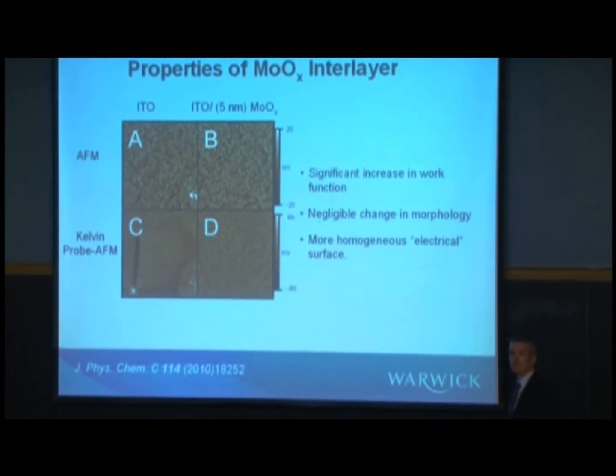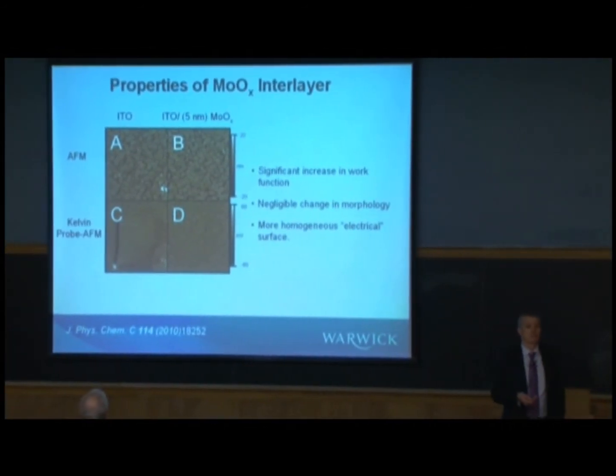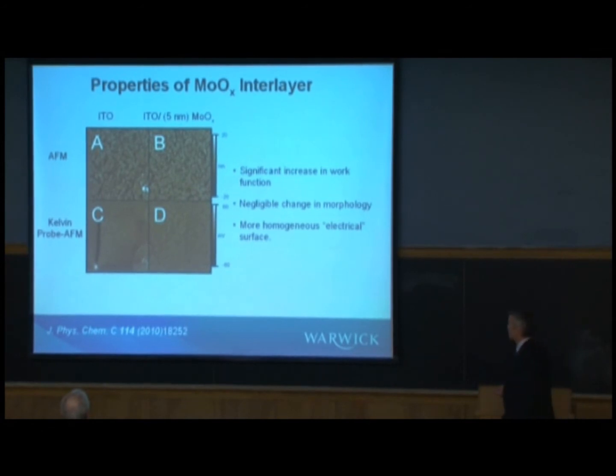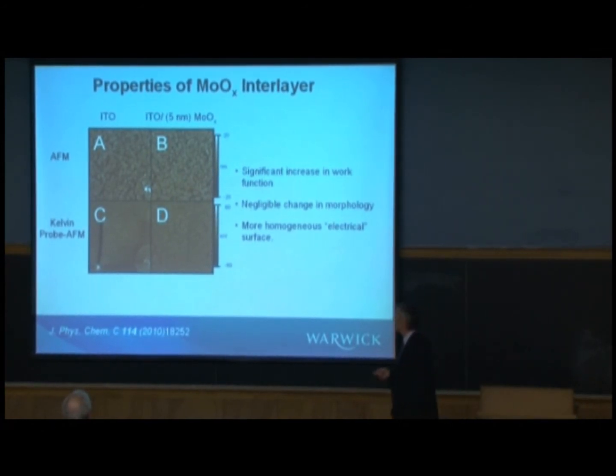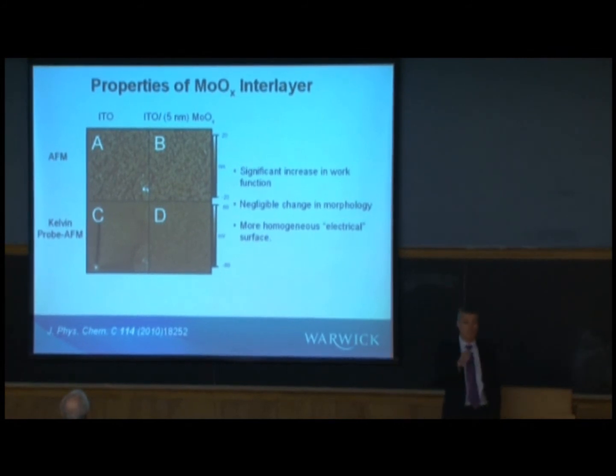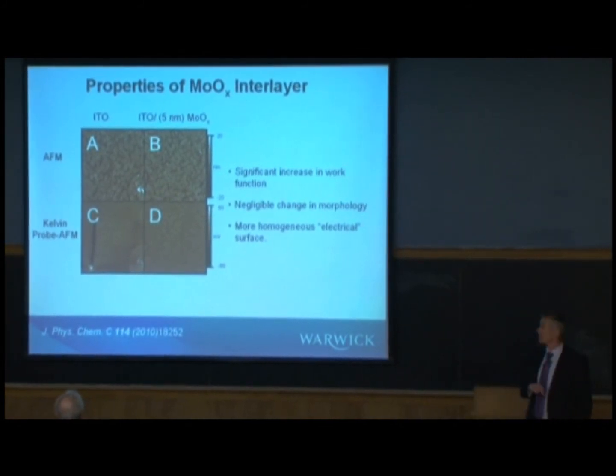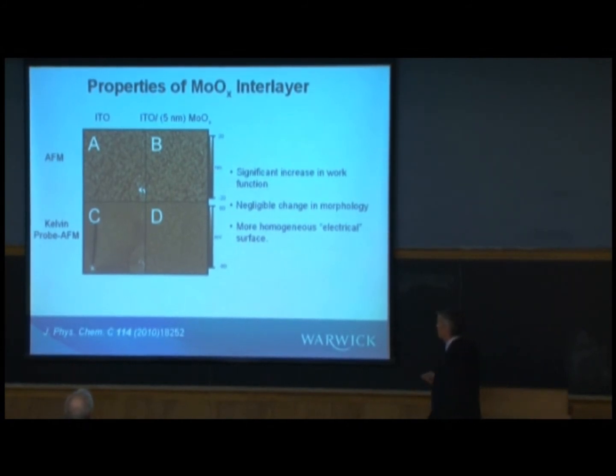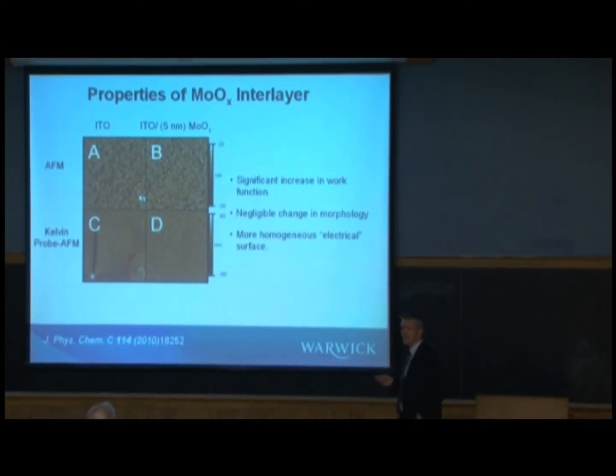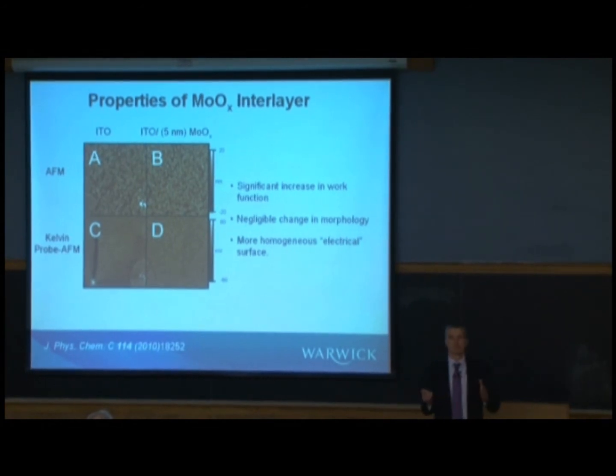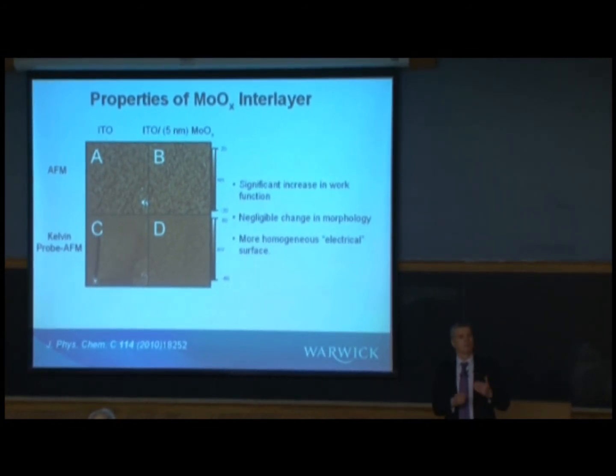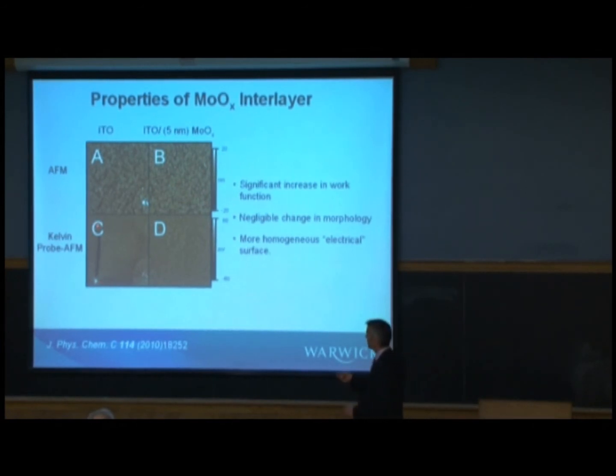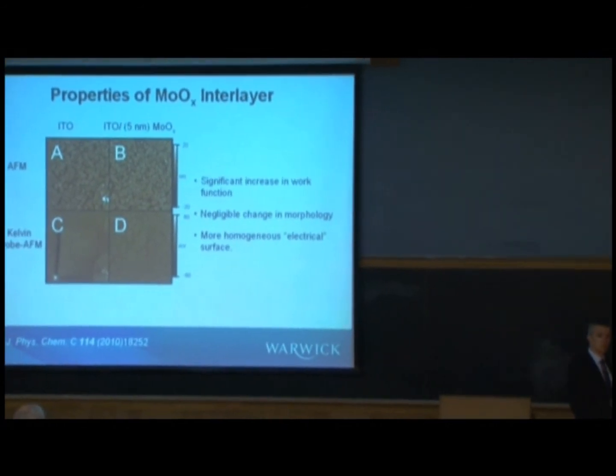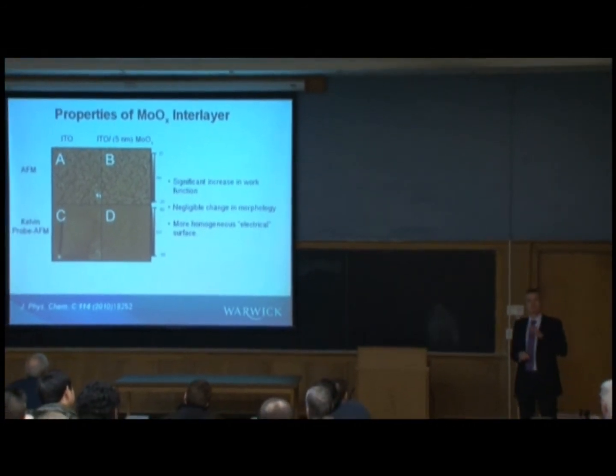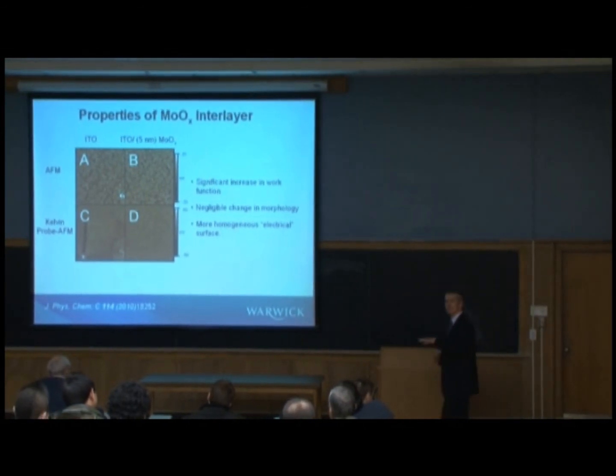These are Kelvin probe AFM images of the same surfaces before and after molybdenum oxide coverage, and you do see some very significant changes. First of all, the work function increases very significantly when you put down the molybdenum oxide. But also what you find is that the electrical properties of the surface are much more homogeneous when you coat the ITO with molybdenum oxide. And these defects that you see here in the bare ITO, which are very common in ITO surfaces, essentially disappear when you put the metal oxide on top. So you're producing a much more uniform electrical surface for your device.